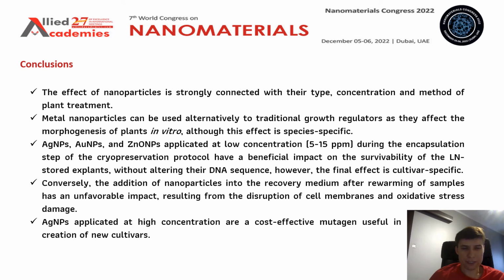Silver, gold, and zinc oxide nanoparticles applied at low concentrations during the encapsulation step of the cryopreservation protocol have a beneficial impact on the survival of the stored specimens without altering their DNA sequence, although again this positive effect may be cultivar specific.